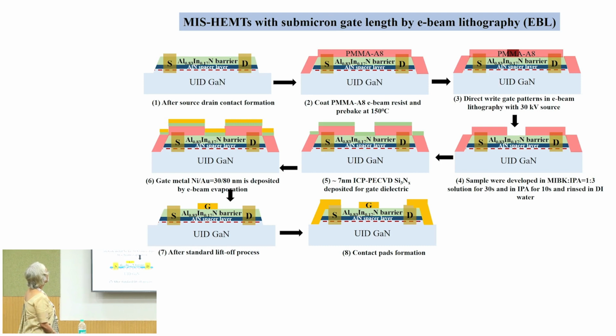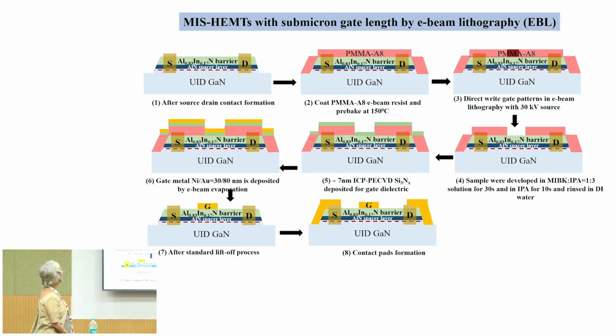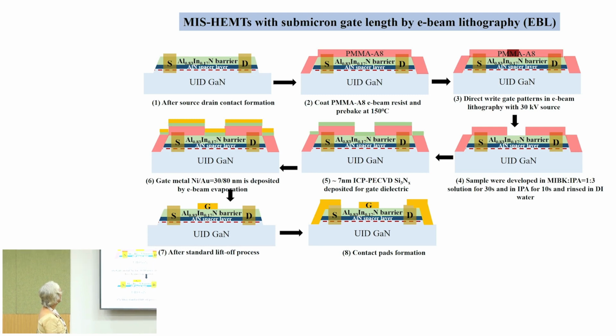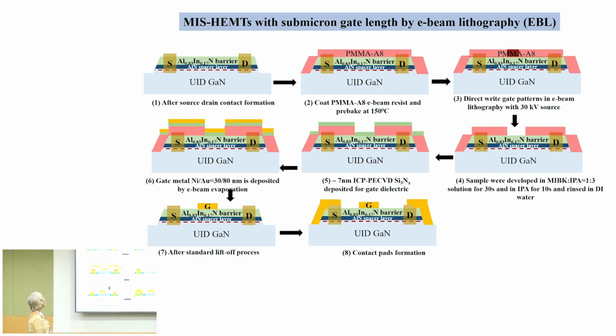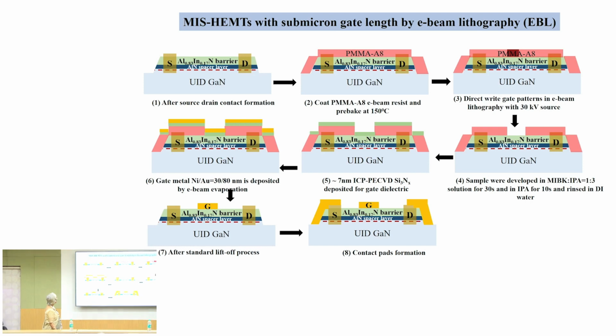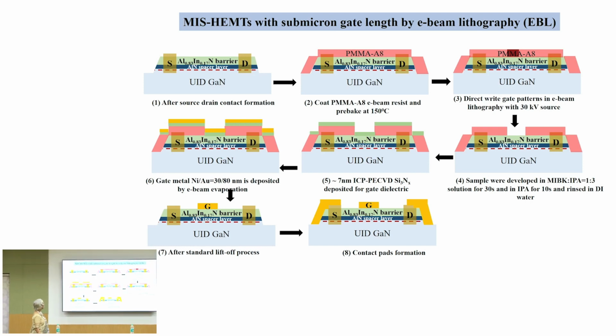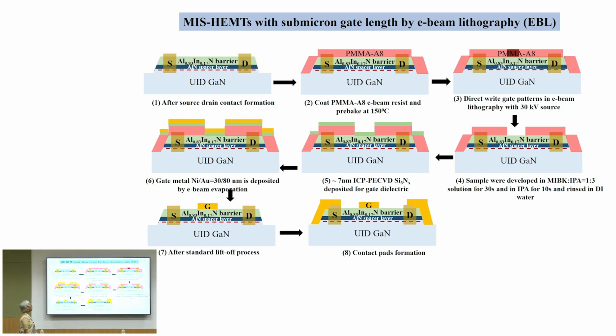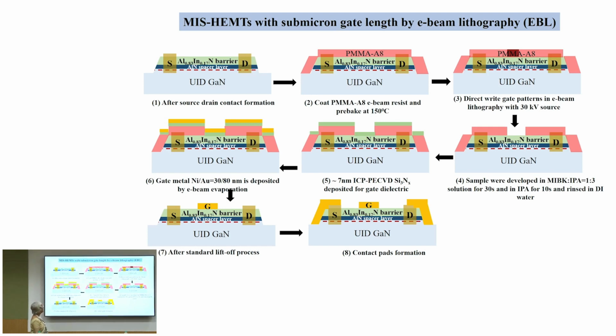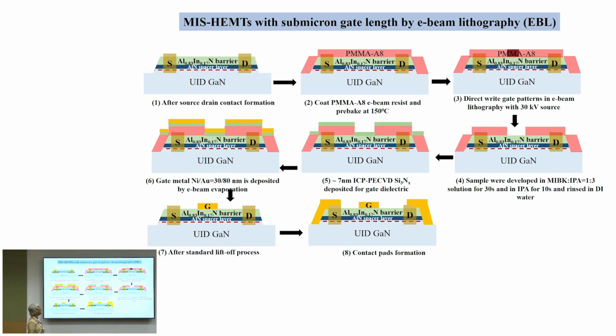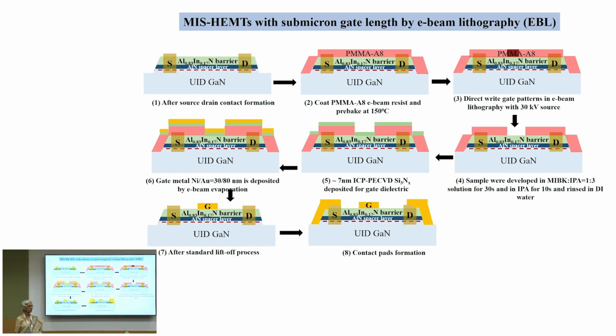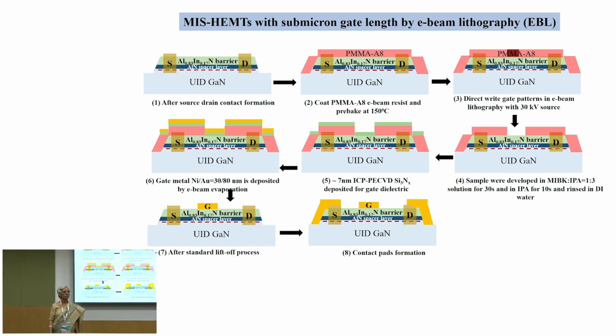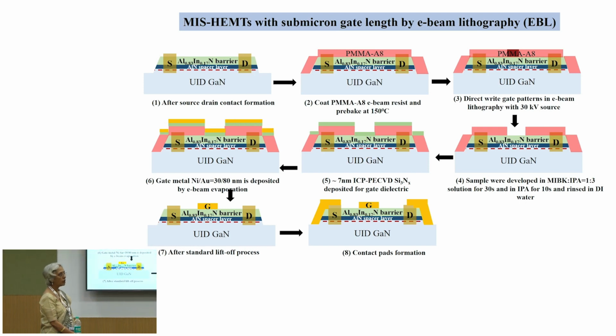So, I have started with the substrate where the source and drain have already been fabricated. As you can see here, we have the aluminum indium nitride barrier layer and the source and drain contacts are already given, and on top of that now we are doing the e-beam lithography. We are using PMMA A8 e-beam resist and directly writing the gate pattern in e-beam lithography with a 30 kilovolt source, and these are for gate lengths of approximately 250 nanometer.